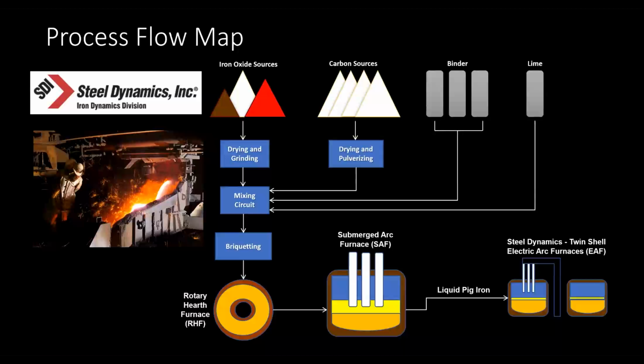So it goes to the rotary hearth furnace for our initial reduction. It goes to the submerged arc furnace where more reduction occurs and melting, then we tap the hot metal and send it to the electric arc furnace. This is actually a picture of them tapping the hot metal out of our SAF.